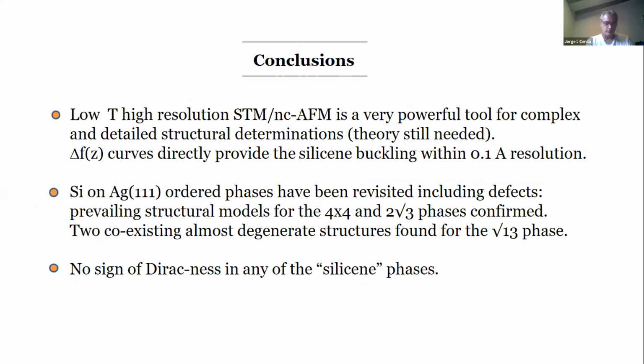So the conclusions of this part will be that I think that working with non-contact AFM is extremely interesting. Complementary with STM, it's extremely powerful. It really helps you in trying to determine these structures. One of the main achievements experimentally is to obtain the direct buckling in silicene within a very good resolution, typically below 0.1, not always, but in most cases below 0.1 angstrom, directly from the frequency shift curves. So I said, we've visited all the phases. I think we made a very neat determination of the most complex one, the big one, the square root 13, in agreement with many previous works.